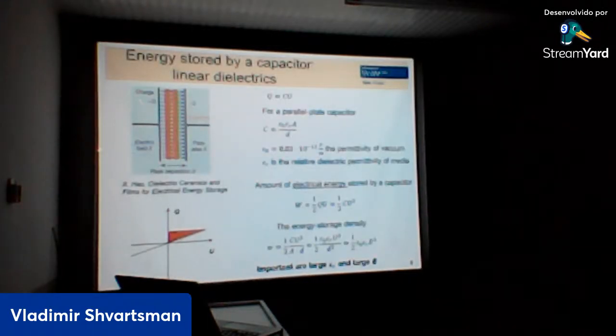So, basic parameters. When we take a classical dielectric capacitor and apply a voltage U between the electrodes, we can store a charge on the metallic electrodes, which is proportional to the applied voltage U. For this simple plane parallel capacitor, it's a well-known relation for the capacitance: it's proportional to the dielectric permittivity and area of the electrodes, and inversely proportional to the thickness between them. The energy stored by this capacitor is a simple expression: 1/2 charge multiplied by voltage, or 1/2 capacitance multiplied by the voltage squared. The density, when we normalize it to the volume, is proportional to the dielectric permittivity and the square of the applied electric field.